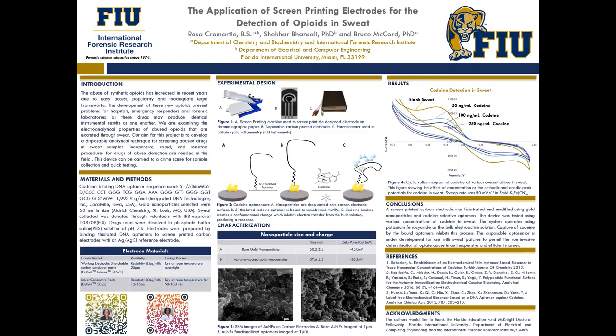So to wrap up this presentation, or this poster, in a sense, this presentation shows the fabrication and the modification of screen printed carbon electrodes with the modification using gold nanoparticles and selective aptamers for targeting cocaine. This device was tested using various concentrations of cocaine in sweat.